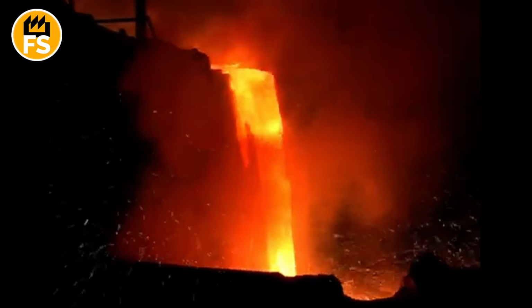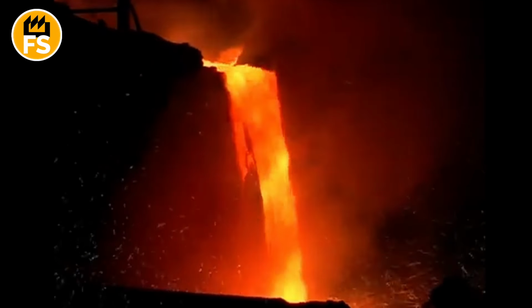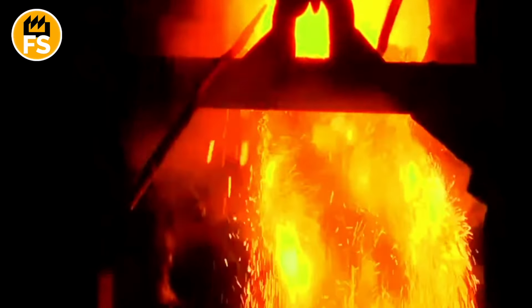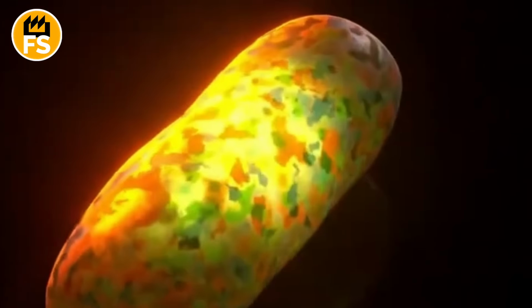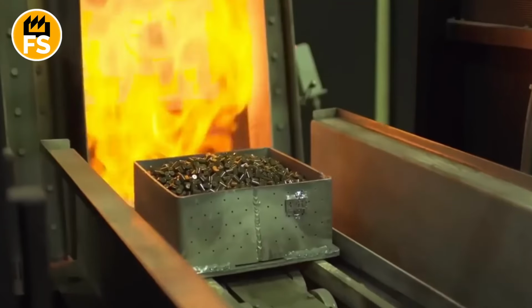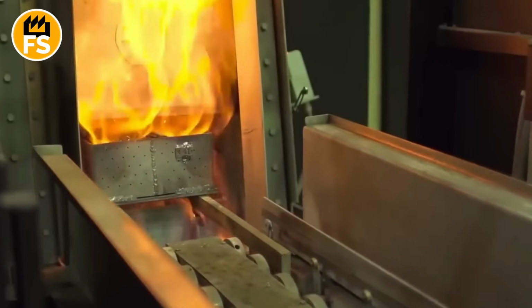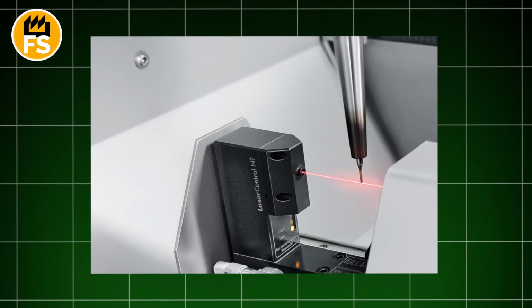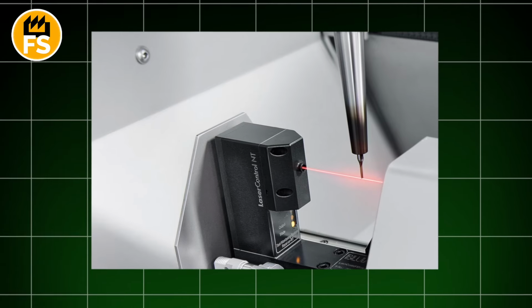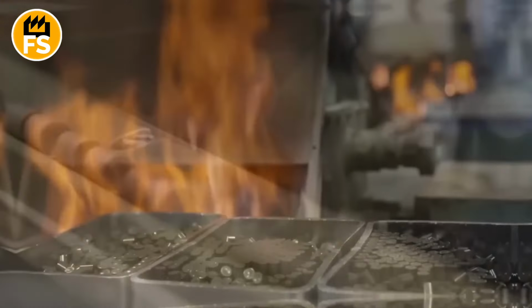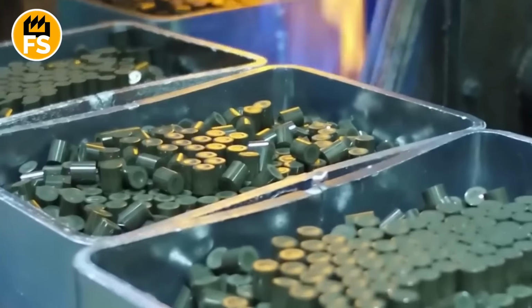There, at a temperature of over 3,000 degrees Fahrenheit, these pellets are baked for many hours. During this process, called sintering, the powder particles fuse together, and the pellet turns into an extremely hard, dense, ceramic-like substance. It becomes so strong that it can withstand the extreme temperatures and pressures inside a nuclear reactor. Each pellet after this undergoes laser control, which checks its dimensions with micron accuracy. The next step is assembly. These small black ceramic candies are carefully, one by one, loaded into long, thin tubes.